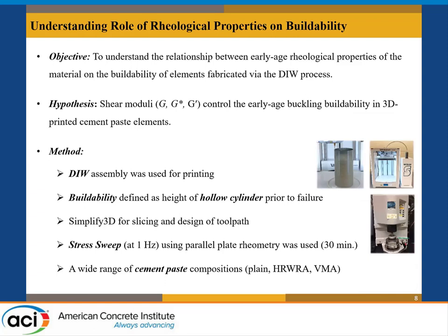The objective here is to understand the relationship between the early age rheological properties and buildability. I refer to early age because most of the deformations occur in the first 30 minutes. Most of these systems fail while they're being printed — failing in their first initial 30 minutes before the rise of shear moduli. We hypothesize that shear moduli control the buckling behavior in these systems, because buckling is related to elastic properties of the material, and shear moduli and elastic properties are interrelated.